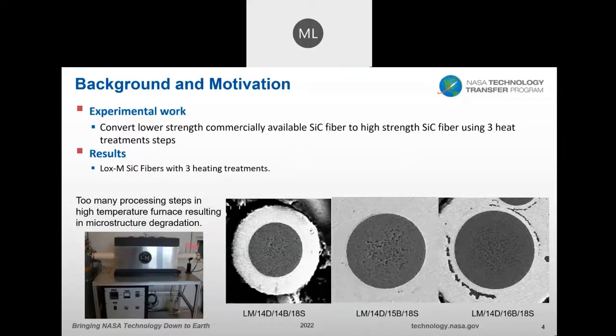For example, if I put in a sample at 7:30 in the morning, I really cannot remove it from the furnace until late in the morning. So it's a long process in which these fibers are exposed to these high temperatures. And as you can see in these SEM images, there's degradation seen in the core of the fiber, or throughout the fiber cores. Next slide.